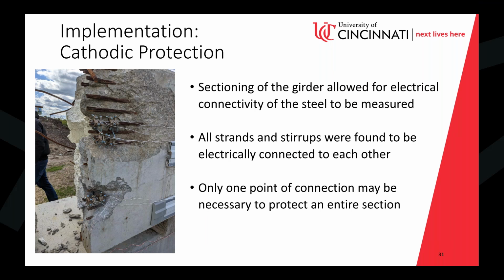And one of the major findings we got, thankfully right off the bat, is that each of the strands in these sections we were testing, so even within these 16 to 20 foot strands, is electrically connected to the other strands in the section, presumably through the stirrups, which cross all of them inside. So in order to employ cathodic protection to a box beam bridge, assumably you actually only need to make one point of connection per, every so much distance, and the steel within that girder is all electrically connected. So you're going to protect all of the steel off one point of contact, which is great.